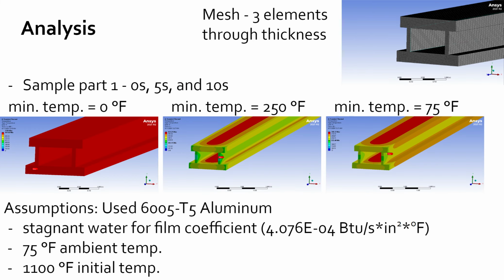To help with the quench box, there were thermal transient heat transfer analysis models to be run for each of the 3 sample parts given by Shape. We used 3 elements through the thickness for the mesh of each part. Each model depicts 0 seconds, 5 seconds, and 10 seconds through the cooling process. The assumptions were 6005 T5 aluminum, stagnant water for the film coefficient, which is just used for the analysis of the cooling, and an ambient temperature for the solutions, as well as an initial temperature.